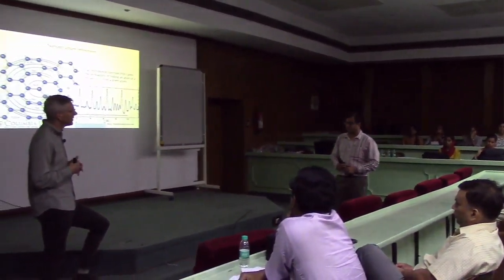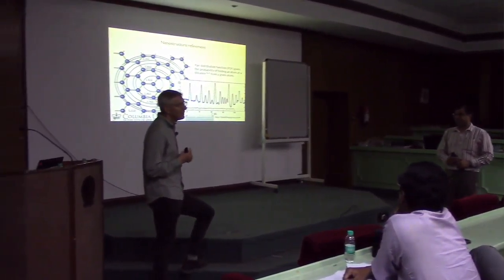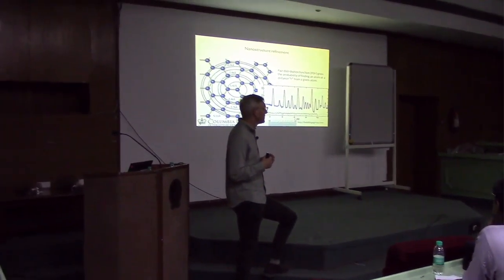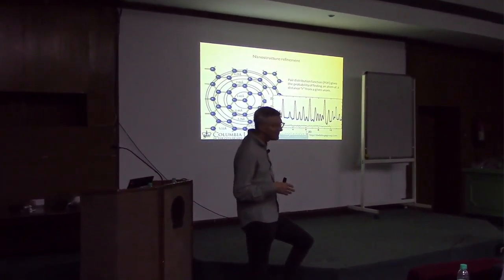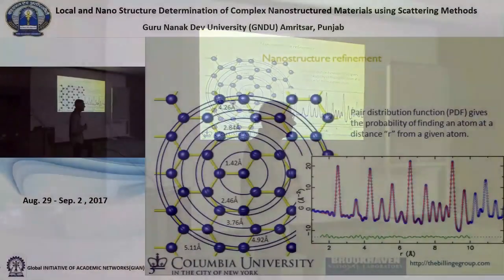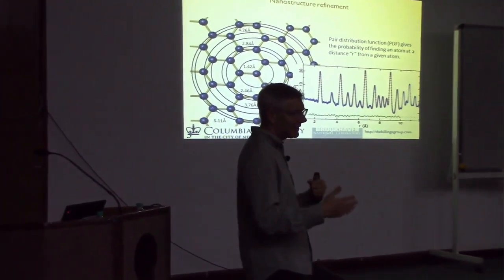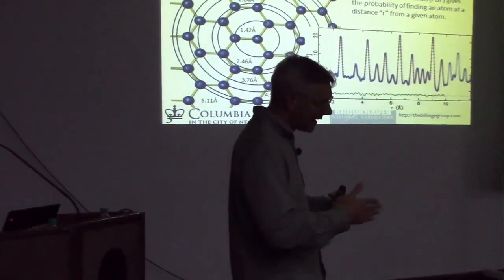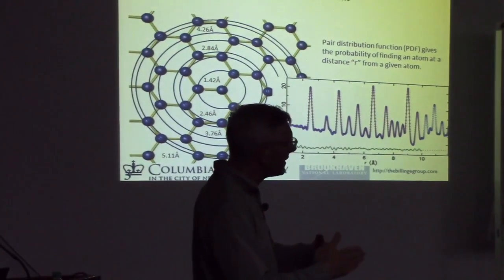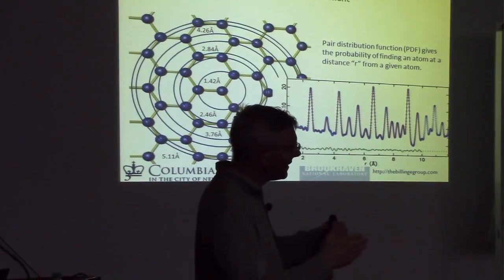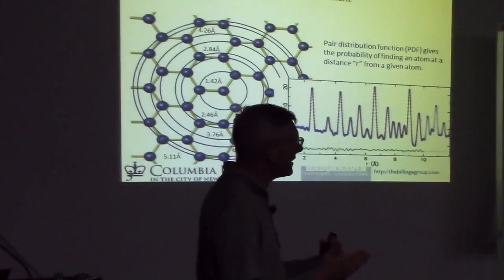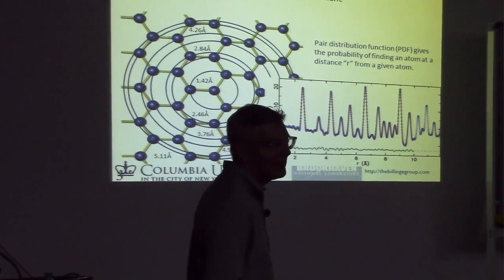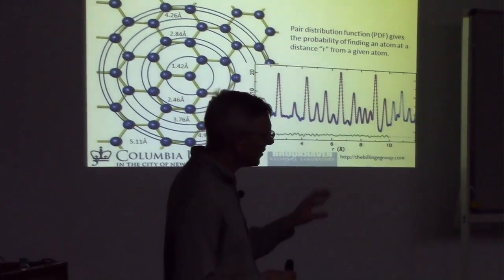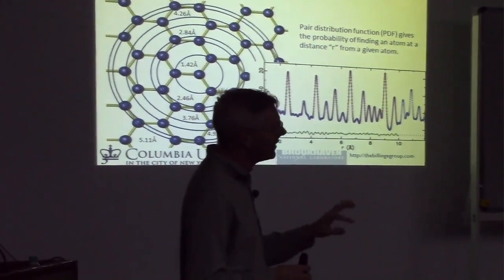So I have one beautiful example that we've been working on recently on pharmaceutical drugs. And we're often not going above 12 inverse angstrom. Even though we have a synchrotron that goes very high, we don't bother. And it's because, in that case, we're mostly interested in the intermolecular correlation function, how these molecules act. And because there's only weak van der Waals bonding between them, the signal itself is quite broad, and there's actually no benefit. So if you pick the right problem, you can use a not so high Q.